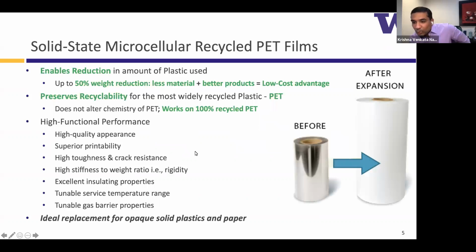So what happens when you apply this technology, the semi-continuous process technology, to recycled PET, which is PET made from post-consumer recycled bottles, right? What happens is it enables reduction in the amount of plastic used per application by about 50%. You can use 50% less weight of plastic to achieve the same application needs. So imagine a coffee cup. Instead of having 8 grams of material in a cup, you could do the same job with 4 grams of material.